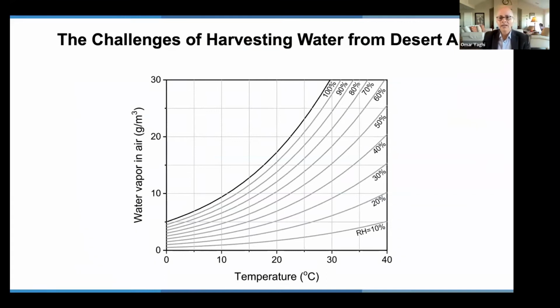So why is it that these machines that are advertised on the internet don't work? And why is direct cooling a problem? Here's the psychrometric chart. It's a plot of the water vapor in air versus temperature. And these are the humidity lines. And I've colored the humidified region in green and the desert regions in pink or light brown. But you see here that if I'm in a city where the temperature is 30 degrees C and the humidity is 20%, if I was to extract water from that air, I have to cool down the air to 4 degrees Celsius to be able to extract the water.